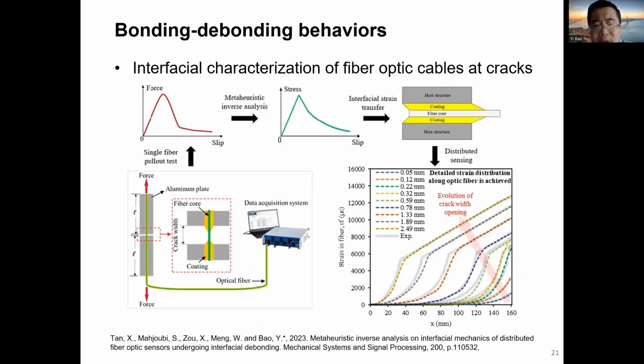And then we conducted further research to understand the interfacial mechanics for fiber optic sensors undergoing the interfacial debonding. So we did the single fiber pull-out testing to characterize the interfacial mechanical property, and then we developed a mechanical model to describe this interfacial debonding. So with the mechanical model, we were able to predict the debonding behavior pretty accurately. And this really enhanced our understanding of the interfacial debonding behavior and also provided us a theoretical basis to quantify the crack opening width. This work has been published in a paper. So I will not elaborate the details, but if you have interest, you can either read this paper or talk to me later.